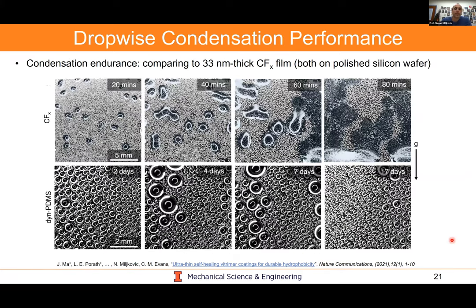And then finally, what we have going on right now is a long-term study looking at how long these could last. This is just a schematic from the paper that we published, comparing it to typical polymer film, where within 80 minutes, the entire polymer film will delaminate, whereas our surface shows absolutely no sign of degradation after 17 days. Now, again, this is ongoing. 17 days is not long enough. What we need is more like 10,700 days, but that will take time and we will get there. So please be patient with us.